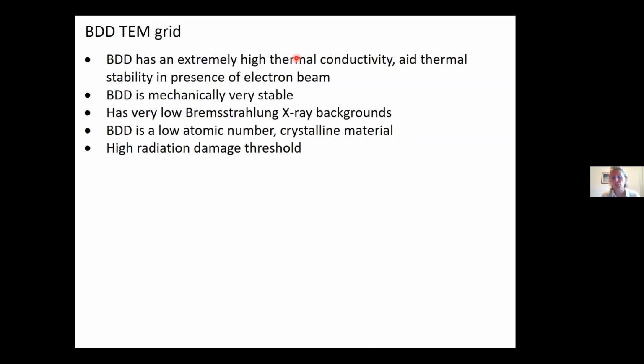So when we start to irradiate structures with the electron beam, the thermal energy from that should dissipate very quickly through the BDD. It's very stable actually, even when it's thin, the way we've got it at the moment, supported. It's got very low backgrounds, and you'll start to see that it's a beautifully crystalline material. So when we do these TEM studies, it's like working with a single crystal. And actually it can tolerate high radiation thresholds, because it's got a high damage limit.